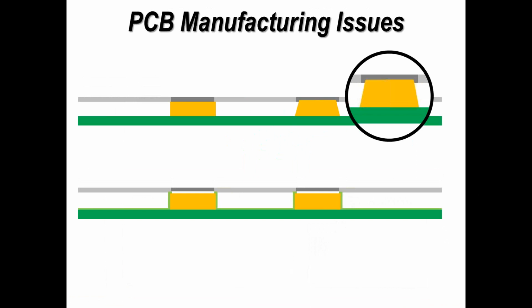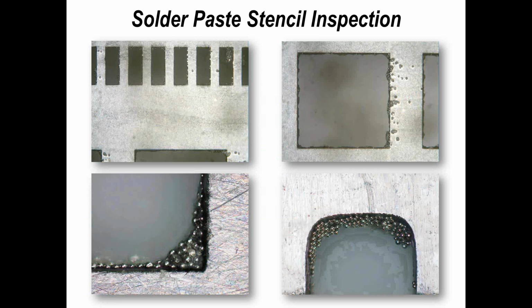And if we're printing onto resist-defined pads, which is popular in many companies, again, the key thing is consistency of height, making sure the stencil is in contact and not deformed in any way. Resist-defined pads can work, but again, it's down to the quality and consistency of the printed circuit board and the suppliers of that. So if you just have a look at a couple of examples of solder paste stencils. Now, I'm sorry to say that these are actually examples where I visited companies and done quality audits. And these are actually some stencils taken from the storage area and not being used in production. And really, this is very, very poor indeed.